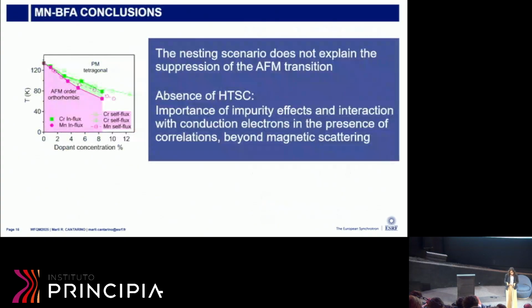But when I look overall at my manganese results, as published, the nesting scenario does not explain the suppression of the antiferromagnetic transition, because we see the same splitting - things are not changing from the electronic structure point of view. The absence of high temperature superconductivity in this phase is interpreted in terms of magnetic impurity scattering the magnetic excitations, which should be important for superconductivity.